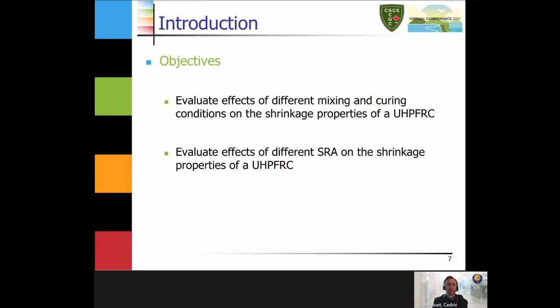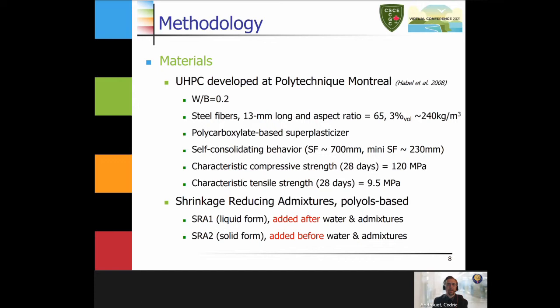So the objectives of this project are to evaluate the effects of different mixing and curing conditions on the shrinkage properties of a UHPFRC, and to evaluate the effects of different SRA on the shrinkage properties of a UHPFRC. For the methodology, we use the UHPC developed at Polytechnique Montreal. It has a water binder ratio of 0.2, 3% volume of steel fibers 13 mm long. We use a polycarboxylate-based superplasticizer so that we can have a self-consolidating behavior, typically a slump flow of 700 mm and a mini slump flow of around 230 mm.